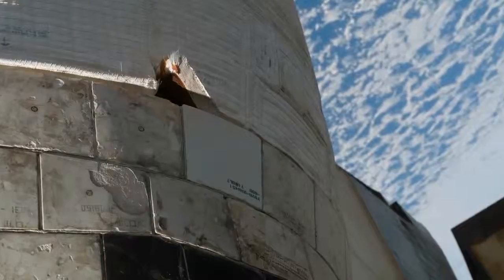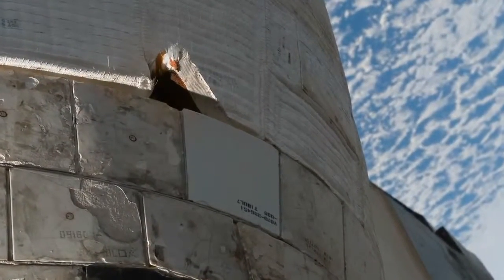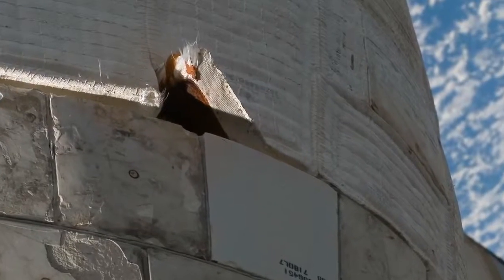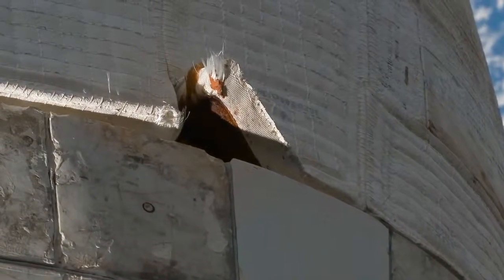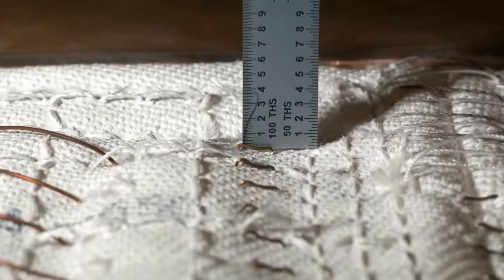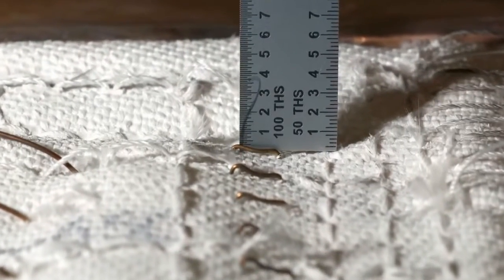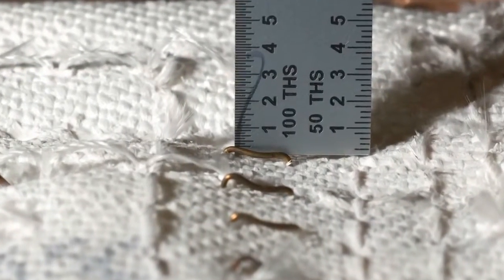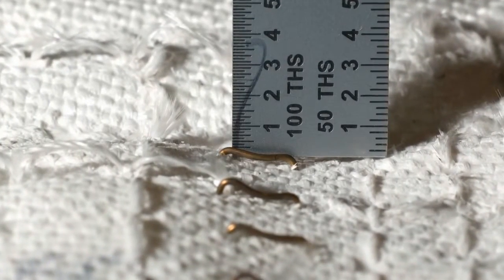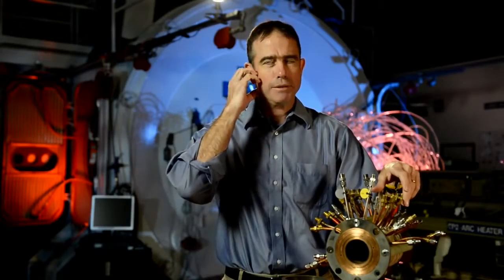STS-117, where we had a blanket that was detached partially from the OMS pod, which is back towards the tail of the orbiter, and we could see it. We were concerned about how to repair it, and so some innovative folks said, hey, we got these medical staples on board. We can send an astronaut out there and use this staple gun to stitch this thing back together. But what we didn't know is, well, what happened with the staples during re-entry? Would they just disintegrate and then the repair would be worthless? Did that test, and that repair worked beautifully.